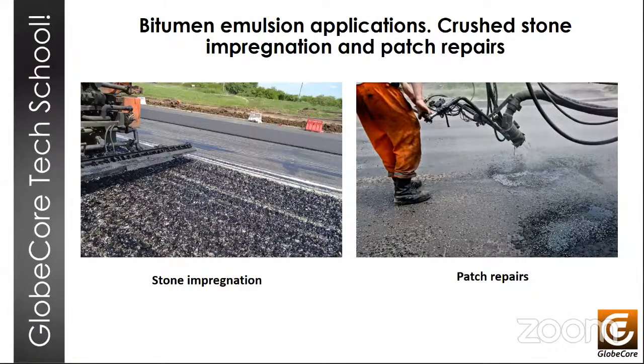There is the patch repairs, and the use of bitumen emulsion does greatly simplify the repair process, and it allows operations to continue well into late autumn and start early in spring with air temperatures just 5 degrees above 0 Celsius. So when using emulsions, it's possible to apply them on wet materials because cationic bitumen emulsions ensure pretty fast formation of a binder film and high adhesion of this film to the surface of most aggregates, even wet, and generally rather good quality of the repair works. Next slide, please.